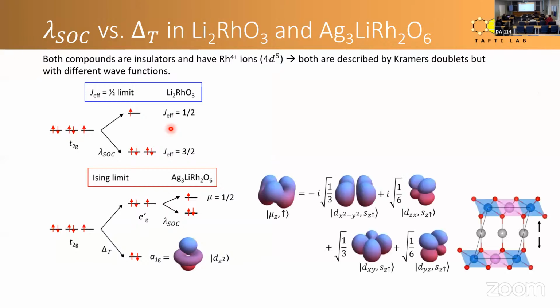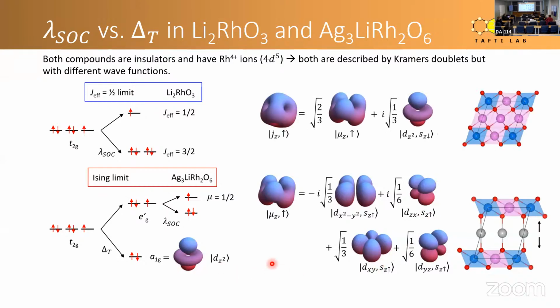In fact, we can plot them. So anybody could basically draw the d orbitals and superpose them, and you can draw how they look. So here is the way that the spin half states look in silver lithium rhodate. Notice that it's a linear combination of d orbitals, but it has no z squared in it. Now you add z squared, right? And then the shape of the spin orbital wave function changes.